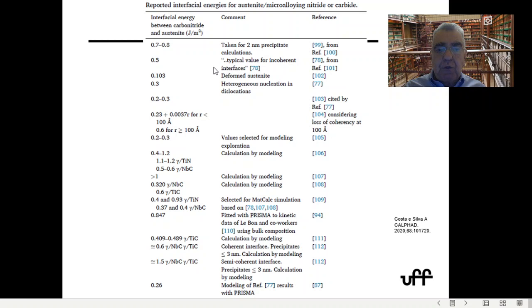If you go to the literature and you look into the interfacial energy between austenite and nitride or carbides, there's values everywhere. I mean, you can find from 0.1 to 1.5 joules per square meter. So essentially what becomes is you have a very, very sensitive model to a given parameter. Then this parameter varies immensely when people fit or measure or whatever. So it becomes a very dangerous exercise because you can almost fit anything by adjusting this little parameter.